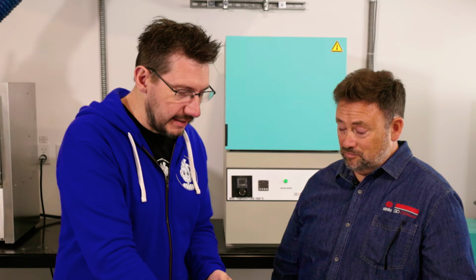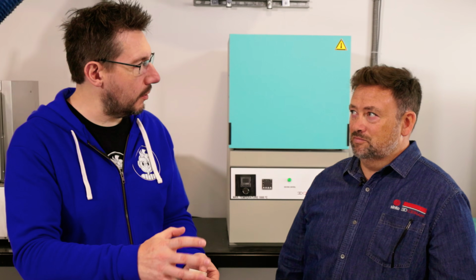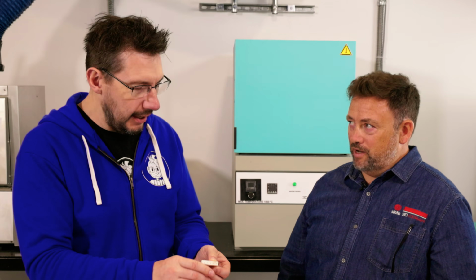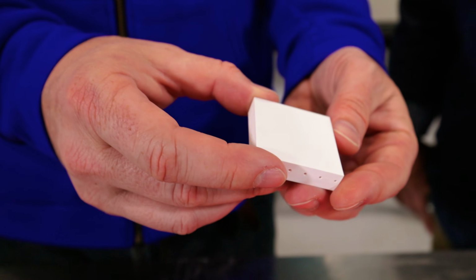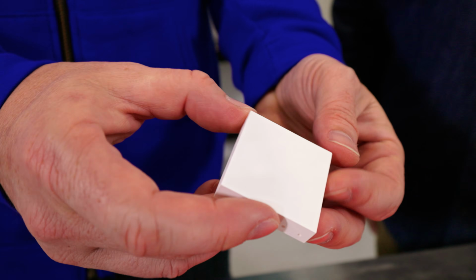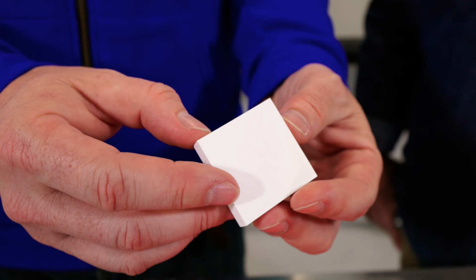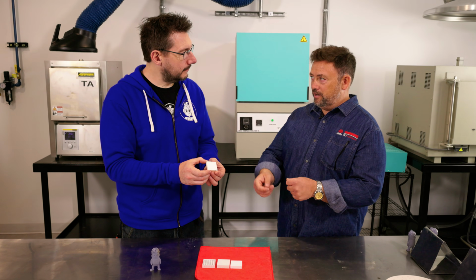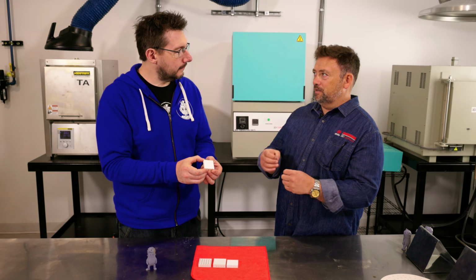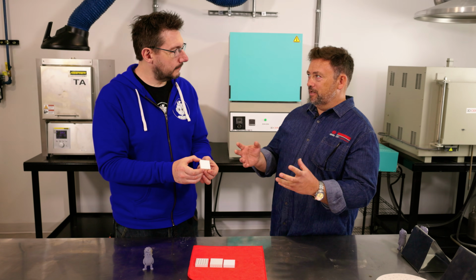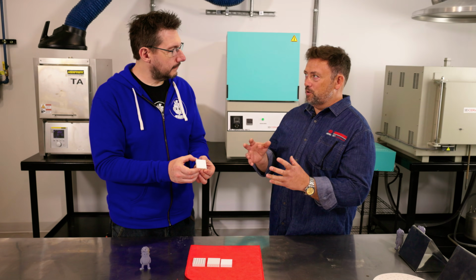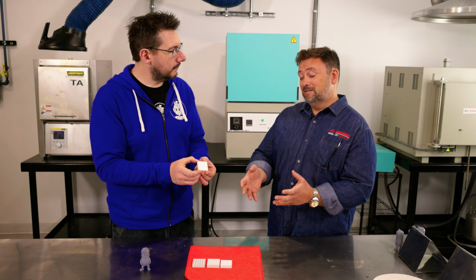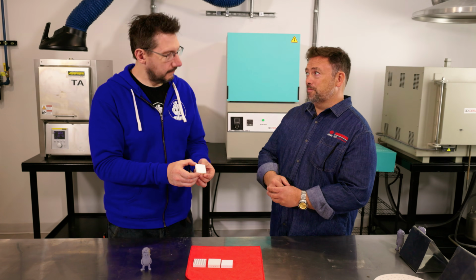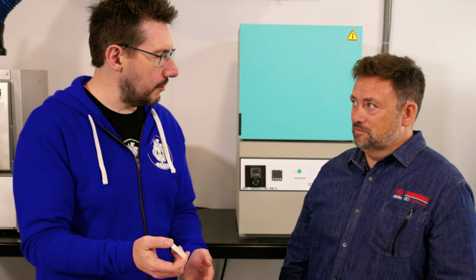So then the other process is longer because you're having to slowly cook out the material. Correct. This one though, because it's pure ceramics, you don't have to take as long? Right, and you're not worried about the organic polymer popping and exploding and burning, and you get carbon and you never know what. You do know what's gonna happen, and you know that if you go too fast, it will pop. And ceramics, you're putting this under 1700 C, 1800 C, and it can hold.